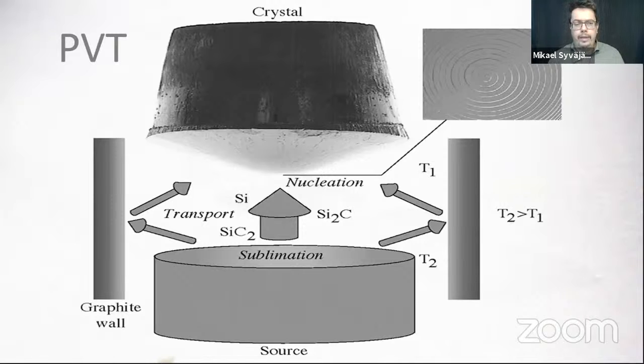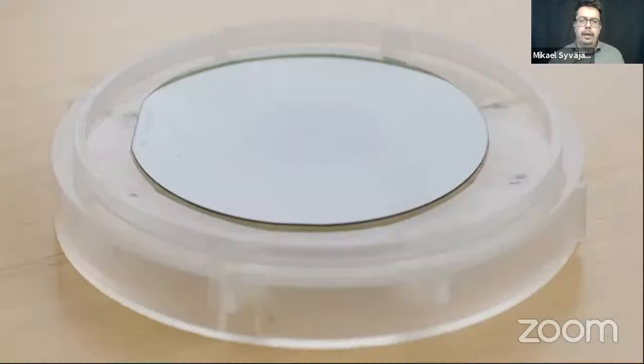So this is now very established for silicon carbide, and there are even commercial companies doing this material. The aim is to grow bulk material from which wafers are cut and polished, and those are used for making thin films and then device processing for further studies. But in the 90s, everything was very, very new in these things. So we also explored the PVT growth of silicon carbide, and all my papers from that time are of course on defects. So we had defects and tried to understand them.